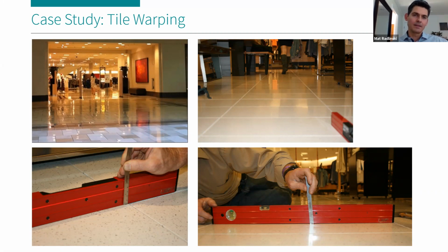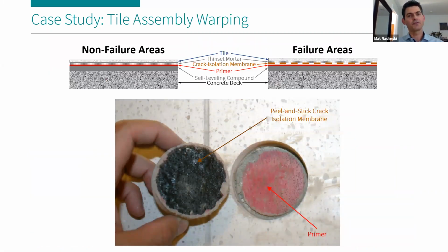Next slide. We don't always have the luxury of being able to compare good and bad areas, but in this particular case, we did. What we discovered is that there was a very clear difference in terms of installation components in the areas exhibiting failures. And those areas apparently or reportedly included locations where there were underlying cracks in the concrete slabs or elevated decks. The contractor tried to mitigate the presence of those cracks with installation of a crack isolation membrane right below the thin-set mortar.